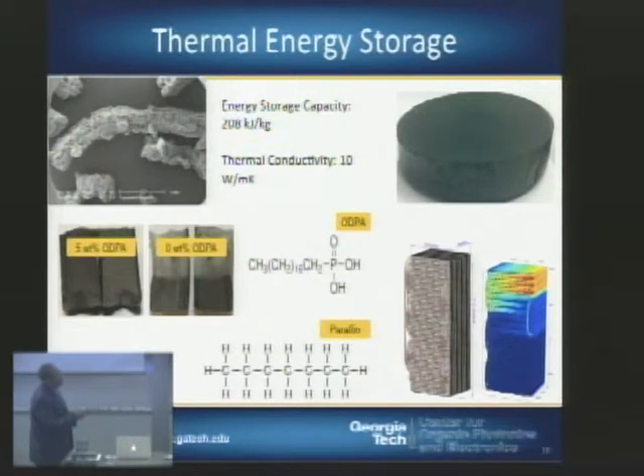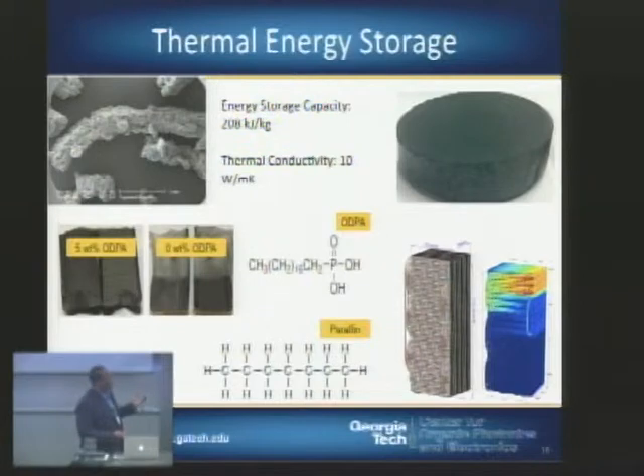And what you'll find is that we can go from a material that has a thermal conductivity of less than 1 watt per meter K to something on the order of 10, all the way up to about 25 watts per meter K. So now you have a material that's as thermally conductive as stainless steel, but it has only about a 15% drop in the overall thermal storage capacity as compared to pure paraffin.